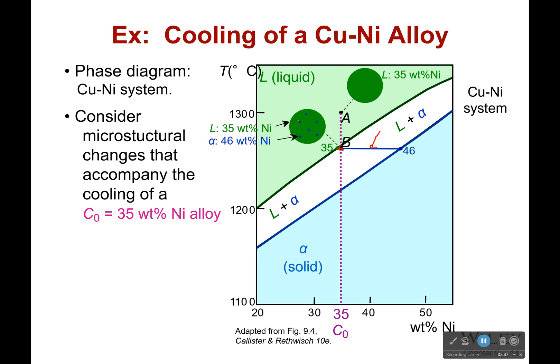But you can see that these little dots of solid have begun to appear. If I continue to cool it, those solid dots get bigger and bigger. So now my liquid is 32 weight percent nickel and my solid is 43 weight percent nickel.